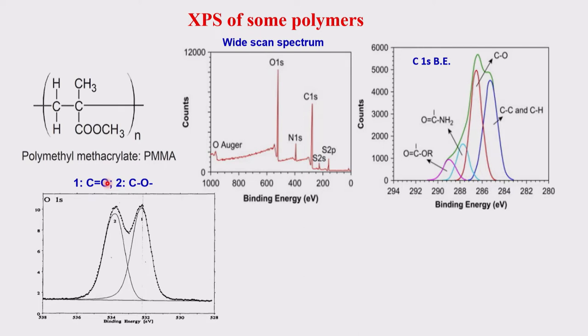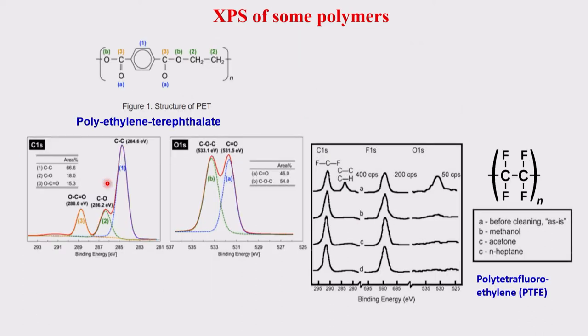Let us look at more polymer examples. There are different types of carbons in this polymer: carbons attached only to carbon, carbons attached immediately to oxygen on both sides, and carbons attached to oxygen on one side. The carbon attached only to carbon has the lowest binding energy around 284.6 eV. The next, attached to one oxygen, is around 286 eV. The carbon with two oxygens is around 288 eV. So you get peaks at roughly 284, 286, and 288 eV.